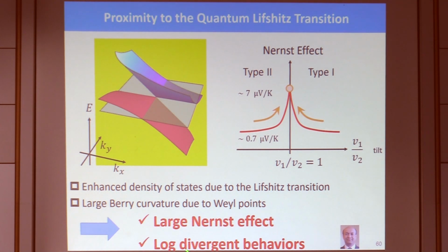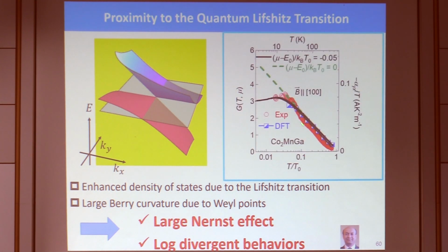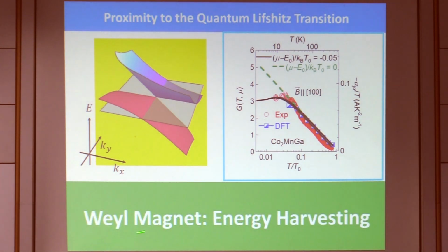At the same time, the theorist Pallab Goswami predicted that if there is such proximity to this quantum Lifshitz transition, there has to be a logarithmic temperature dependence of the transverse thermoelectric coefficient. And in fact, the observation does show this logarithmic temperature dependence. This is another reason why we see a large Nernst effect. So we think the Weyl magnet would become a very useful magnet for energy harvesting.